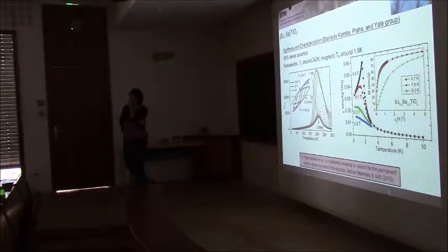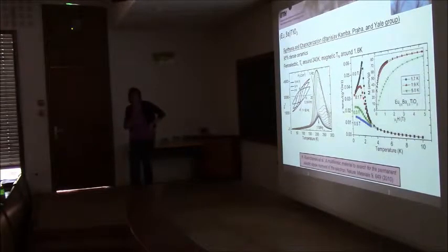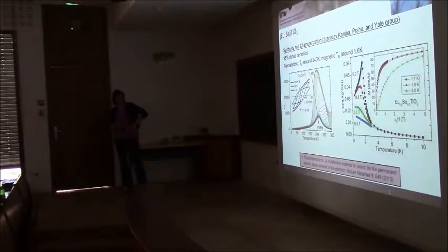And in this case, is the pattern of the distortion now dominated also by the europium, or still only by the titanium? Oh, that's a really good question. Yeah, so if you look at the distortion pattern of the soft mode, at least in the computer where we can calculate it, it has a very large europium off-centering also. Because the europium is so small, it kind of rattles. So the europium, I think, is not doing anything chemically. It's just too little for its space, so it follows the titanium along. Which was also very good. This was a project. We were trying to design a material to measure the electric dipole moment of the electron.